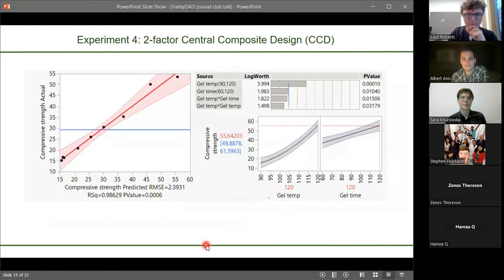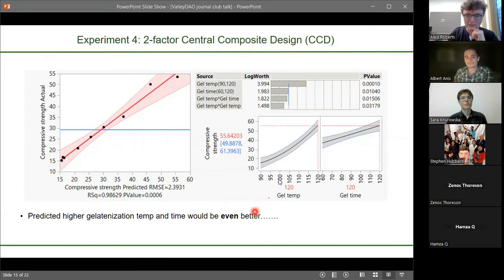So then we did another experiment called a central composite design. Just 9 experimental runs where we just looked at gelation time and gelation temperature, keeping everything else constant. And this helped us get from a compressive strength of about 15 megapascals up to over 50. So it really, really helped. And again, it was just 9 experimental runs because that previous experiment told us what to focus on. And it predicted that even higher gelation temperatures, so it's saying go even higher to get higher strengths, and higher gelation times would help. So that's what I did.